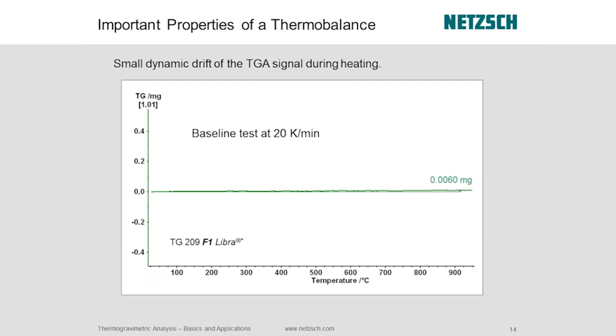So here's a good example then of the drift specifications for the next model, the TG 209 F1 Libra. And you see it's very similar to that F3. We did a test here up to 1,000 degrees C, running a baseline at 20 degrees per minute. And you see as it's being run dynamically, the drift change is only about 6 micrograms. So extremely stable performance behavior in all of our equipment.